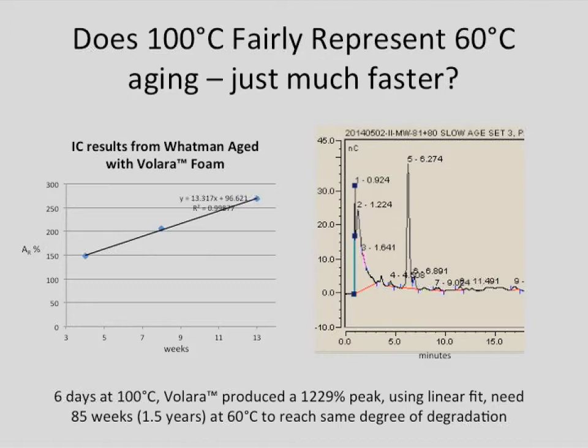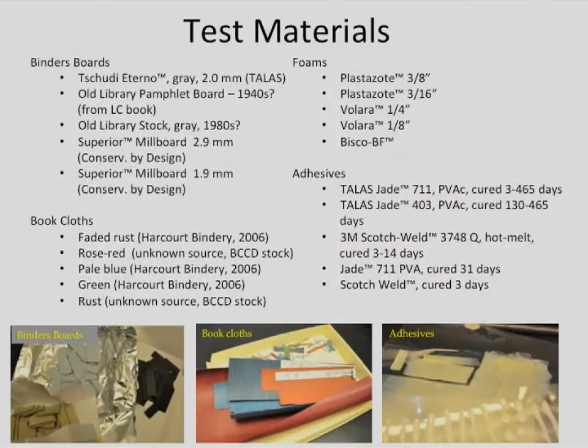What I like to see, though, is that the spectra or chromatograms are similar for a 60 degree and 100 degree aging process. It's just that you have smaller peaks at the 60 degree process. So we think it's a fair comparison.